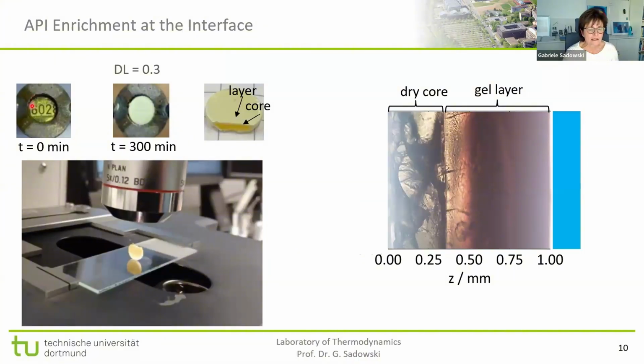And I will show you what the outcome of this modeling was. On the left-hand side, you see the same sample I was talking about before. This is PVPVA with indometacin. It was a clear sample at the beginning. We put this into a water bath, and at the end, after 5 hours, we could see this. The tablet looked completely different, so obviously something happened here. If we then took the tablet out of this metal ring, this is how it looked. If you cut this in pieces, you can really see it has an inner core and an outer layer, and the two look quite different. And this is what we then got for the microscopic image. This is the ASD. Water comes from the right-hand side, so it moves in here.